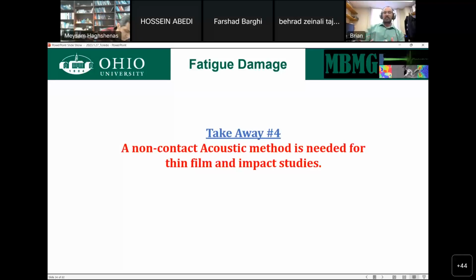The downside to that is you're trying to transfer sound from a metal through air into your sensor. By doing that, the air can act as a huge dampener, and so you lose a lot of your information. But if you change your methodology and use something like a laser vibrometer, you're still detecting the surface. You're not making physical contact with the surface anymore, but you're detecting the surface itself, which means we don't have to worry about losses traveling through air. And that's the methodology that we're approaching.